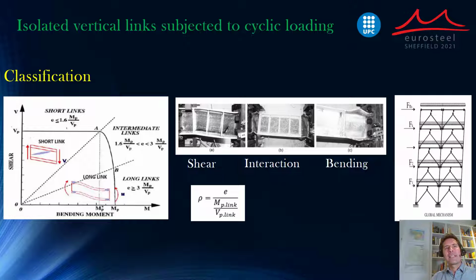If we move now to the geometrical and structural classification of the links, the links, either horizontal or vertical, are classified according to a parameter called ρ, which is the relationship between the length of the link and the ratio between the plastic moment and the plastic shear resistance. This ratio ρ determines whether the link is classified as short, long, or intermediate. If short, the primary failure mechanism is associated with shear. If long, their primary failure mechanism is bending. And if intermediate, of course, there is an interaction of both shear and bending. This classification is defined in Eurocode 8.